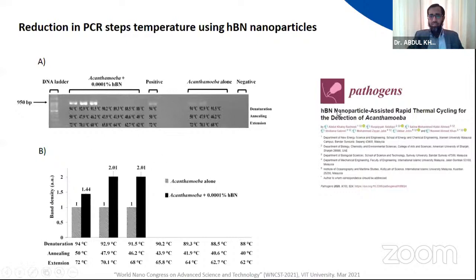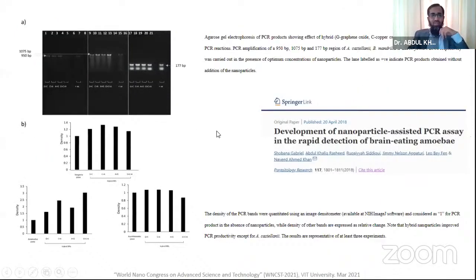We have displayed all the readings here. You can refer to this paper to see all the reductions that we achieved. So first is the yield enhanced. Second is the reduction in the step temperature. The third one, what we found, is you can also reduce the number of cycles required in PCR. Normally, to amplify a single target DNA into millions of copies, there are approximately 40 cycles. What we found is you can reduce the number of cycles so much so that it could be as few as 20 cycles. Within 20 cycles, you can clearly determine whether there is amplification or not, for example, for PCR diagnosis in the case of COVID, you can clearly establish whether the result is positive or not with the reduction to 20 cycles. So I think this will cut down almost 50% of the reaction time, and this has also been established in one of our studies.